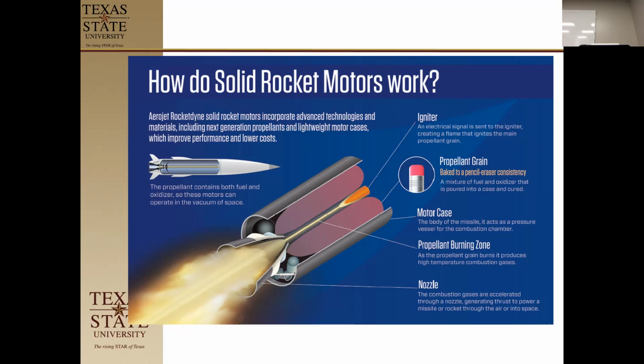So then the propellant here is usually mixed with a butadiene rubber. I'll show you several different formulations. It's usually aluminum powder, ammonium perchlorate, and a binder, which also burns. And so it does create some CO2 as well. And it's done in a consistency about a hard rubber, like an eraser. And you know why? Consistency is very important, but it won't crack.